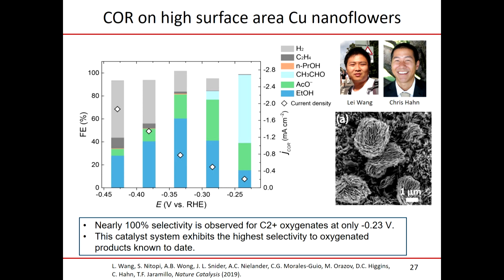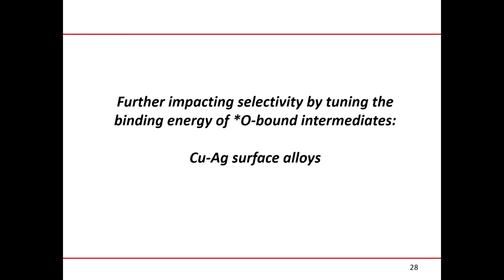Of course, if you tilt the voltage more negative, you'll increase the reaction rate, but you'll start to make more reduced products. And so this is giving you a lever. This is interesting. It's showing you how voltage itself can be a lever in steering selectivity the way you might want it to go. Now, if you want to make a single oxygenated compound, we thought it might be wise to tune the binding energy of oxygen-bound intermediates.